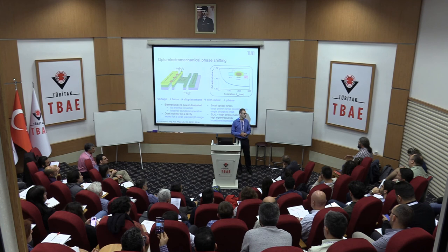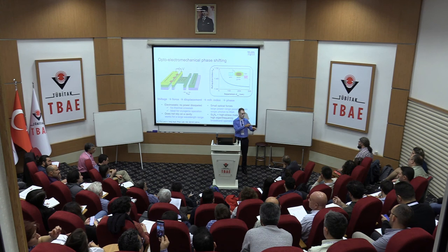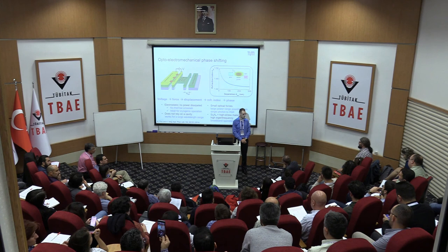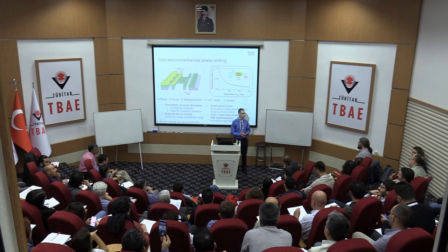Have a local increase in temperature? Well, there are definitely things where people say there's a hot spot, and then the current is actually too large. It exceeds the critical current of the wire plus the hot spot, and then it starts to grow a hot spot and so on. People have a lot of ideas and really try to pinpoint now the exact mechanisms. So I would say the global picture is pretty clear, but there's still a lot of unsolved details in there.